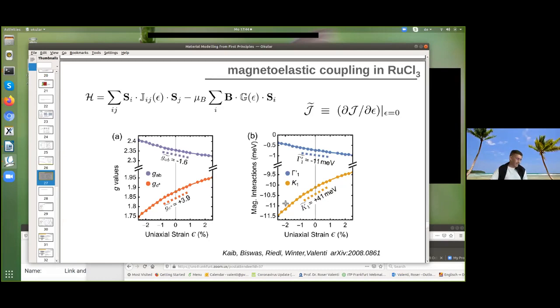So you see the KITP, I'm sorry, I didn't spend a lot of time. The Kitaev interaction and the gamma prime interaction are these dots here. For every value of the strain, let's say at -2 strain, we have a Kitaev interaction of about -11 millielectron volts, while at +2 I have a Kitaev interaction of about -9.5. But what is very strong is the slope, the variation of the interaction with the strain. So it's a derivative, basically.